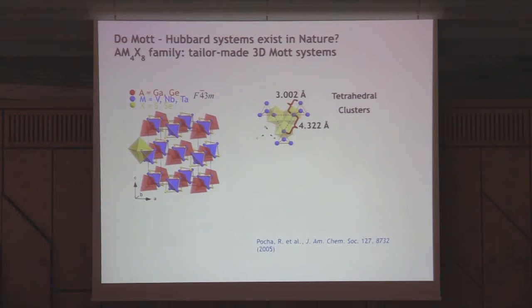So why are these systems so nice? Because all the transition metal atoms form a very compact cluster. The distance between the transition metal atoms here is only 3 angstroms, and the distance between clusters is over 4 angstroms. So the proper treatment is to consider these as small molecules and have molecular orbitals and start filling up those molecular orbitals.